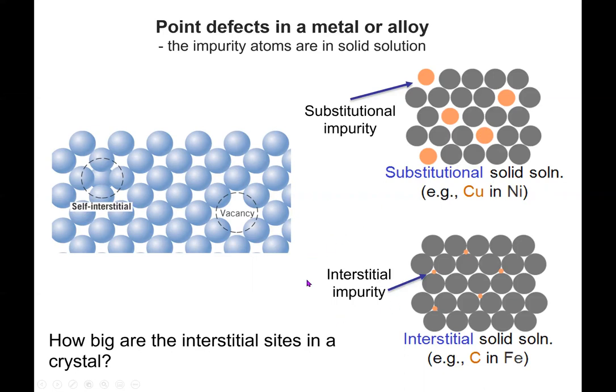Now, we could also take an alloy, a smaller atom, into a host and have it locate at interstitial sites. It's referred to as an interstitial impurity. A good example of this one would be carbon in iron forming a steel. So we'd have a steel structure, the iron, the host, and then the carbon would sit in the interstitial sites. Now, in this picture, it makes it look like it sits perfectly in here. In fact, the carbon is a little bit big. And so it does distort the lattice, which increases the energy of that system. And so we'll see that we can't put a whole lot of carbon into the iron because of this. If you try and push in too much, then the carbon will precipitate out of this lattice and form an iron carbide.